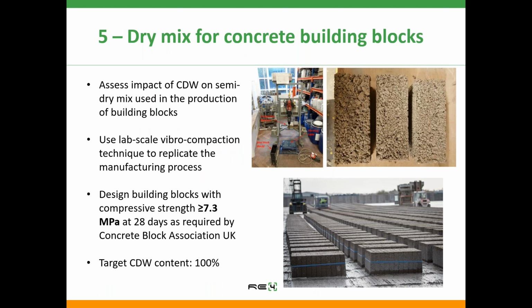The final mix developed is the dry mix for concrete building blocks. The aim was to assess the impact of construction and demolition waste derived aggregates on the semi-dry mix used in the production of these building blocks. So we have used the lab scale vibro compaction technique to replicate the manufacturing process, and you can see the rig in the first photograph on the slide, whilst you can see the building blocks produced in the laboratory on the top right-hand photo. The requirement for these blocks was a compressive strength greater than 7.3 megapascal at 28 days. This is what's required by the Concrete Block Association in the UK.